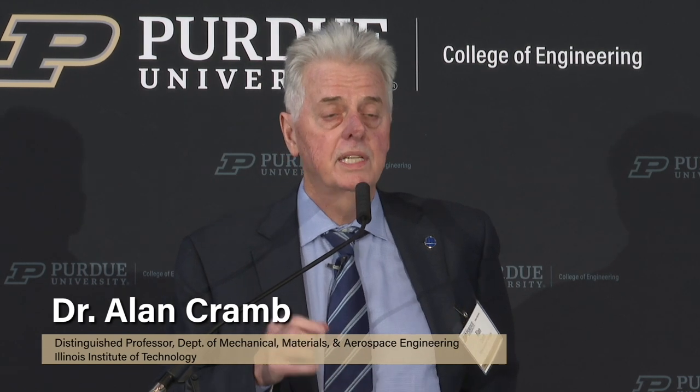These are options. There were people working before on, instead of oxides, making sulfides and then reducing the sulfides at lower temperatures, which is possible also. So there are options, but nothing has reached commercial. Let's face it, if we look at any metal that's more stable than iron oxide, we can reduce iron oxide with it. So there are many options. There are just very few options to do it in bulk at the scale we need the steel for, and at a price that's happening with carbon. That's simple. So the answer is very cheap electricity could change everything, because then you'd have very cheap hydrogen. And that would maybe develop other technologies also.